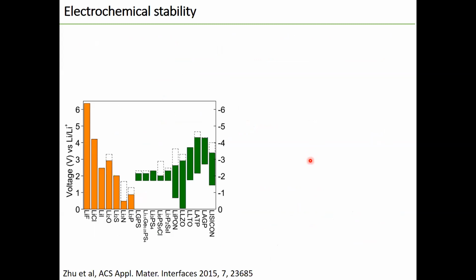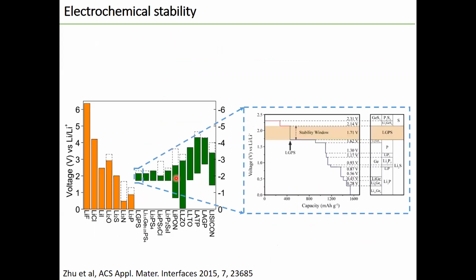However, sulfide electrolyte suffers from a rather narrow electrochemical stability window, which means they will be reduced or oxidized during electrochemical reaction if the working voltage is over the stability window. For example, LGPS has an ultra-high ionic conductivity of 10 millisiemens per centimeter. However, its electrochemical stability window only ranges from 1.7 to 2.1 volts. When worked at high voltage, it will be oxidized into sulfur and some polysulfides. When worked at low voltage, it will be reduced into some lithium sulfide and other polysulfides and other species. This decomposition will consume the electrolyte and bring huge resistance into batteries.